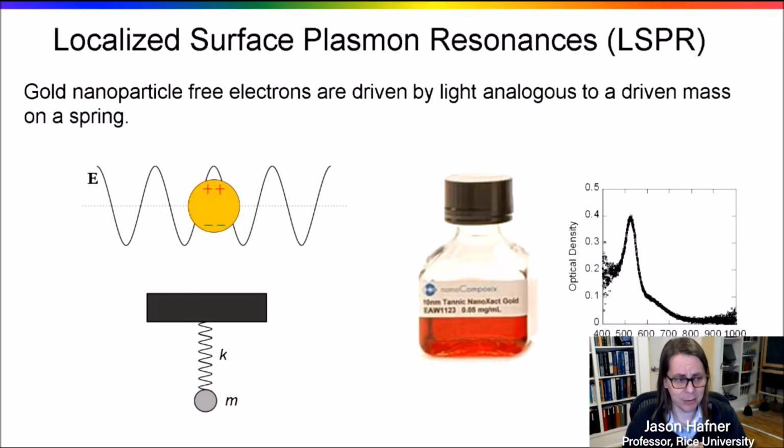And what makes a metal is that the charges in the metal are free to move around. That's why it can conduct electricity. So an electric field pushes a free charge, like the force in an electric field, F equals QE. So as the light goes by the sphere, it pushes charge up. It pushes negative charges against the electric field. And when the negative free charges move down, that leaves the positive atoms uncovered. So you essentially make a little electric dipole in the particle. So you have excess electrons on the bottom, that's negative, and the top is positive. And then the light wave keeps going and it flips direction.